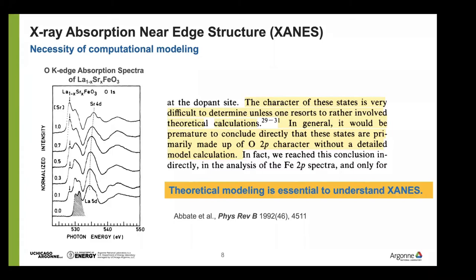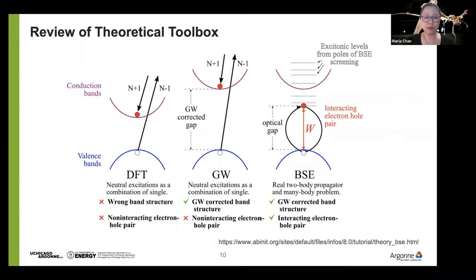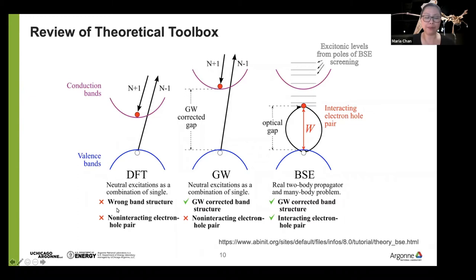There are other experts in the field who have developed great computational codes, and we've heard from a couple in this seminar series. We rely heavily on density functional theory DFT because it gives us the structure responsible for all changes in the material as it is operated or synthesized. DFT is essential for determining structure, and can also roughly determine a spectrum, but it suffers from a wrong band structure and underestimation of band gap.